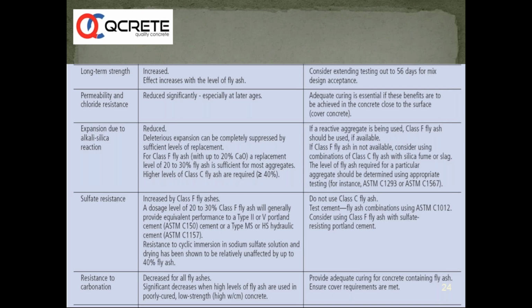Alkali silica reaction is reduced. Sulfate resistance is increased significantly. One of the problems some people and some researchers quote is that resistance to carbonation is decreased when we are using fly ash, but it can be countered by using concrete at definite, required dosages of fly ash addition.